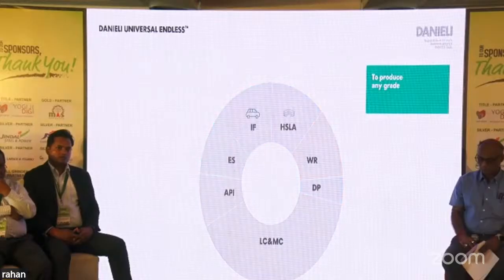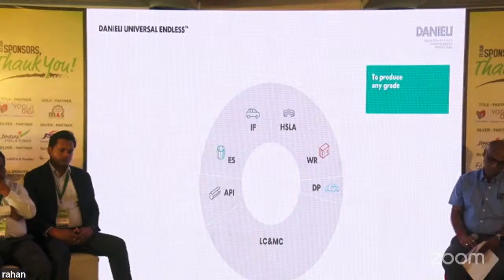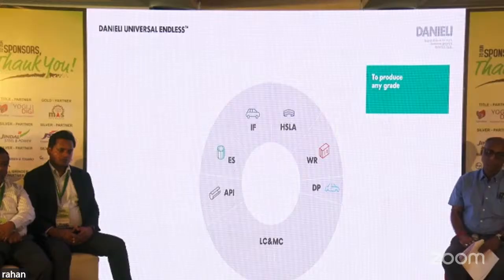Here I mention any grade. You can talk of also the IF, interstitial free, and auto exposed grades. I would like to speak about this. This was until now done conventionally through the slab casters because it needs scarfing. For interstitial free and auto exposed grades, the slabs after they are cast had to be cleaned on the surface. But in case of QSP DUA, we have a provision of also getting these slabs scarfed before they enter the rolling mill, and thereby it's possible to have interstitial free steel also.